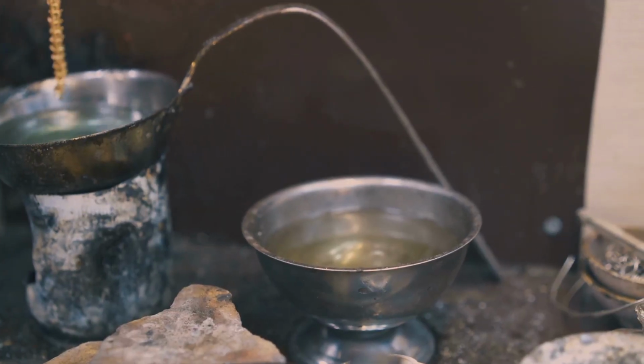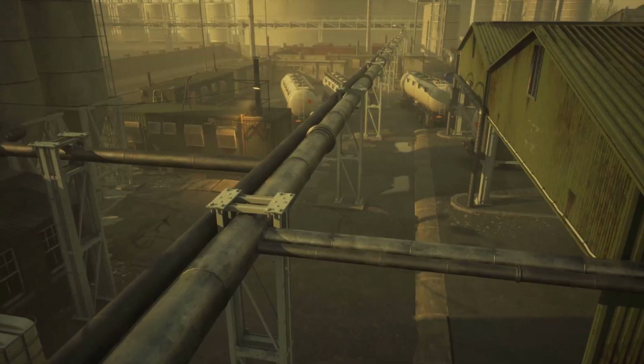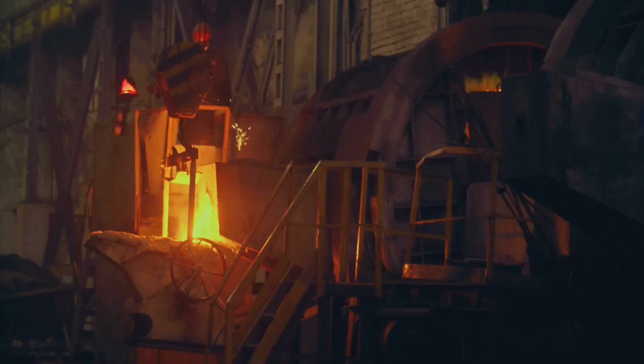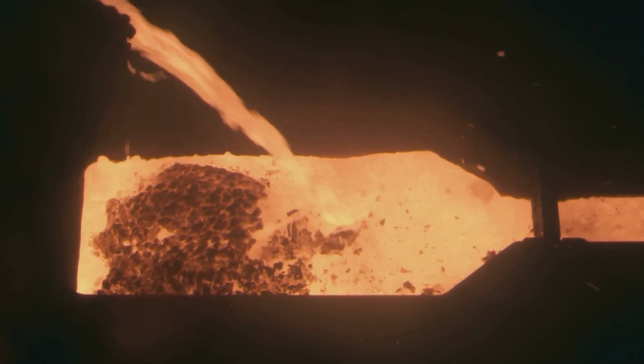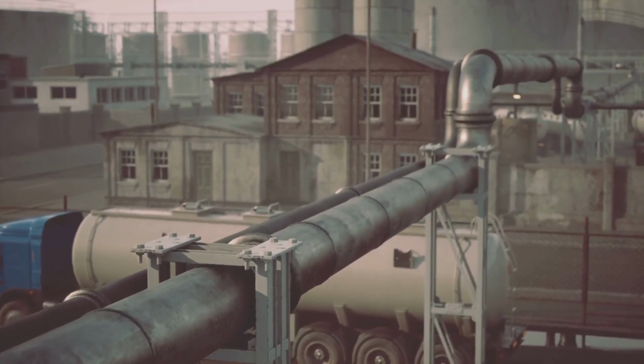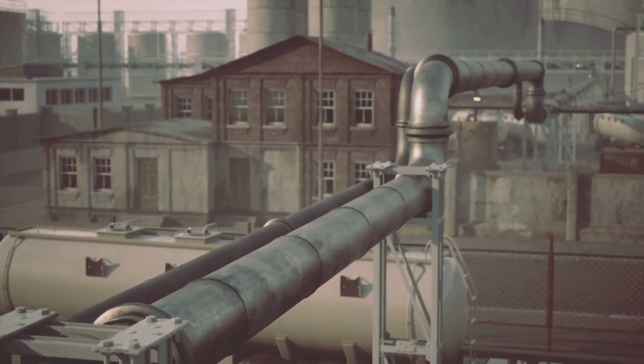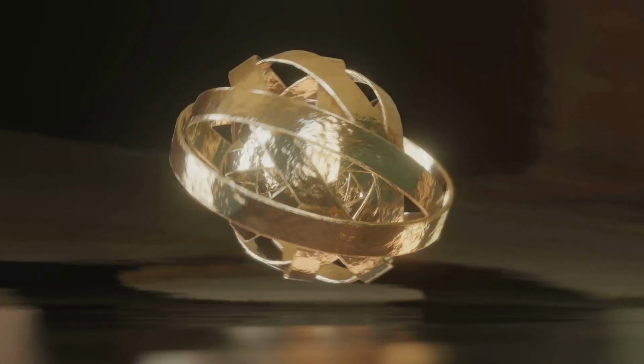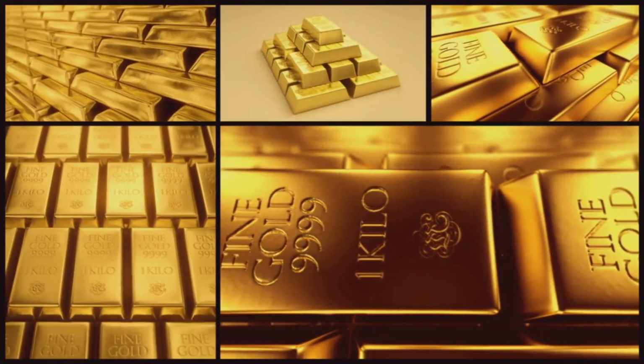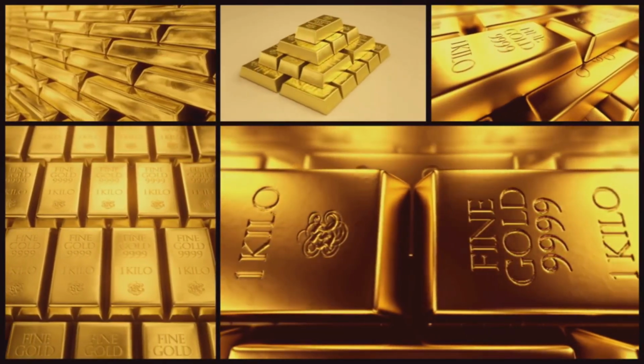Step 6. Refining to high purity. Two main paths. Miller process: bubble chlorine through molten gold, base metals react first and head into the slag, about 99.5% purity, fast and industrial. Wohlwill process: dissolves gold into an electrolyte, plates it back onto cathodes atom by atom, slow but insanely pure, up to 99.99%. LBMA grade.